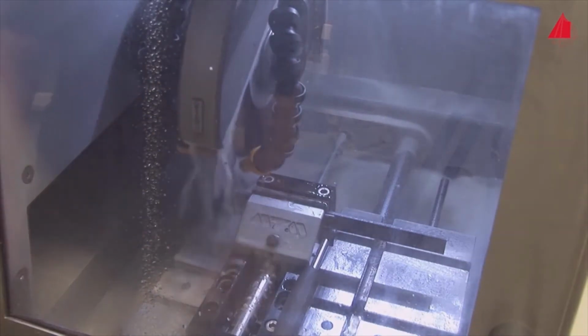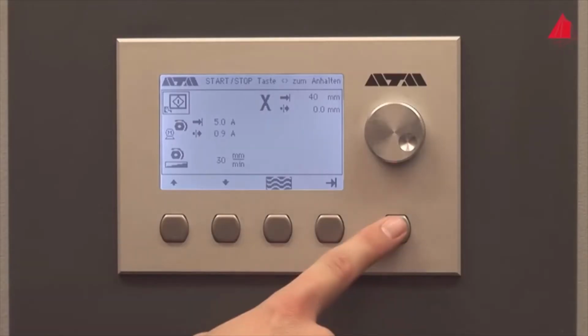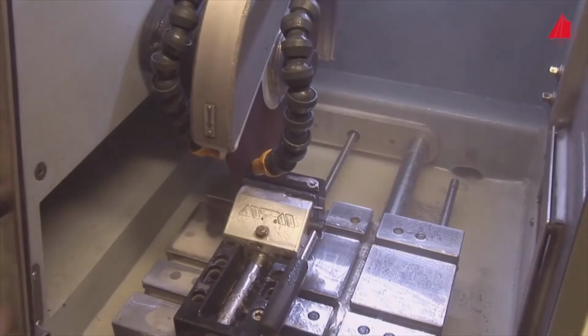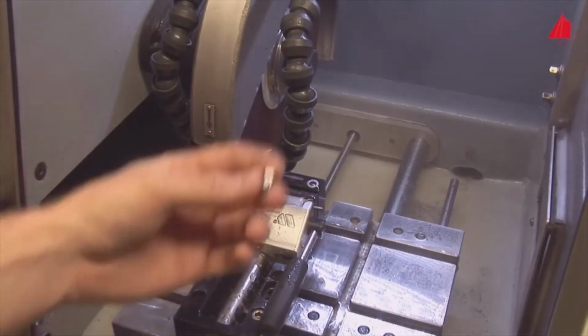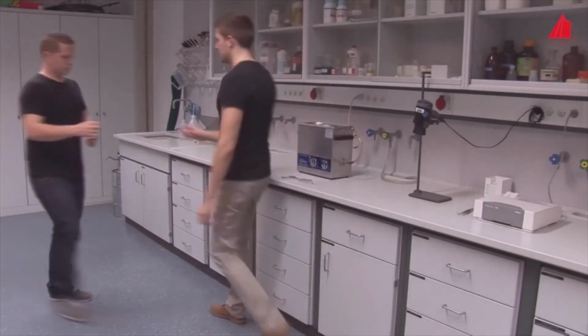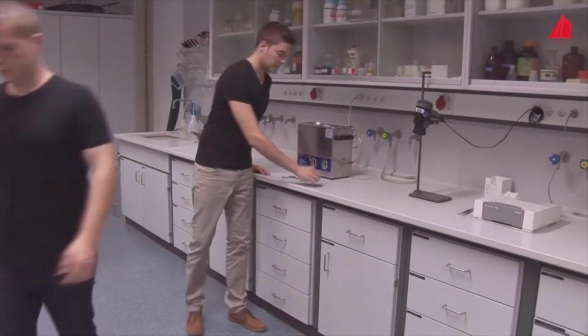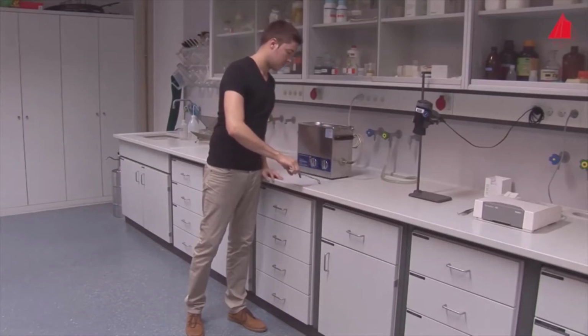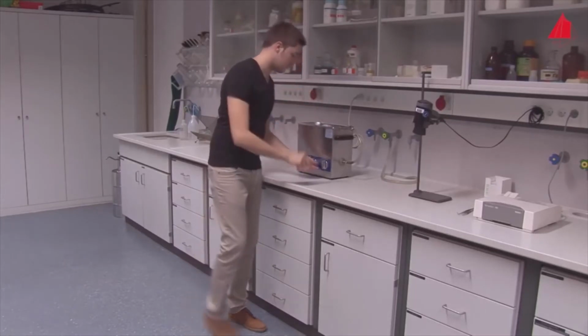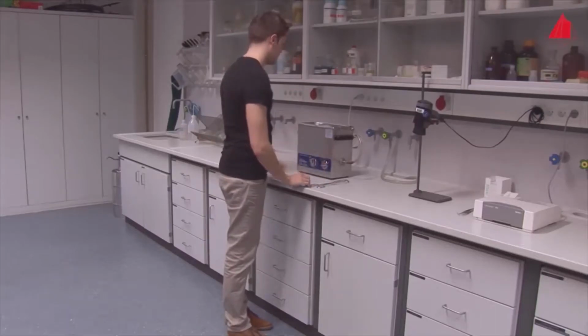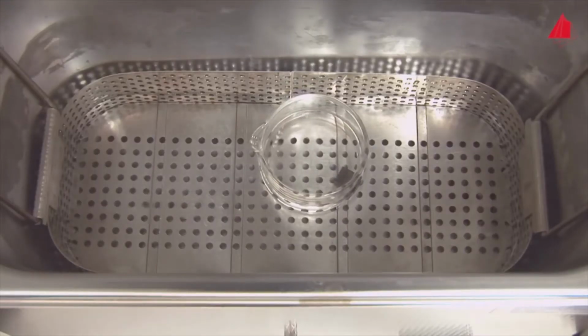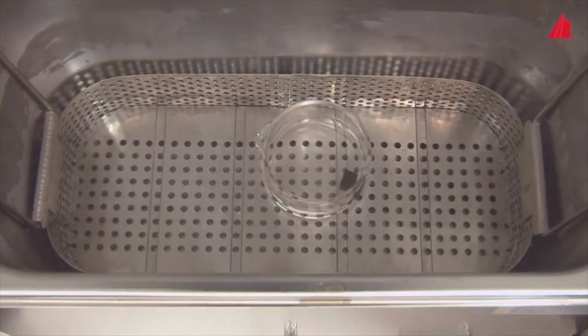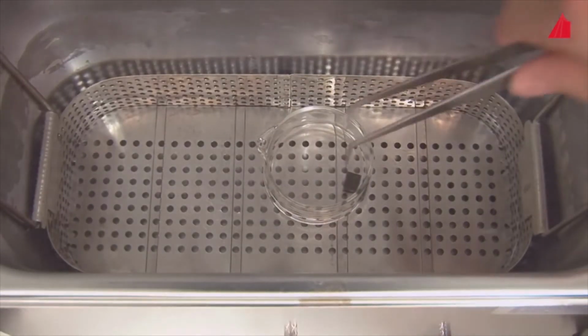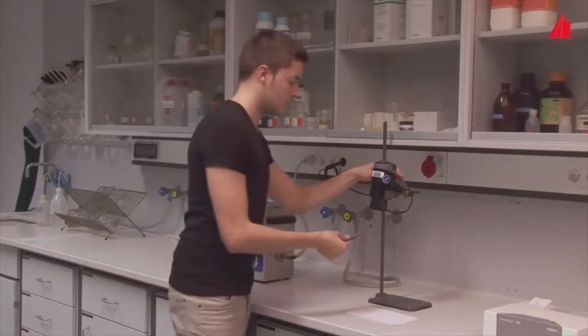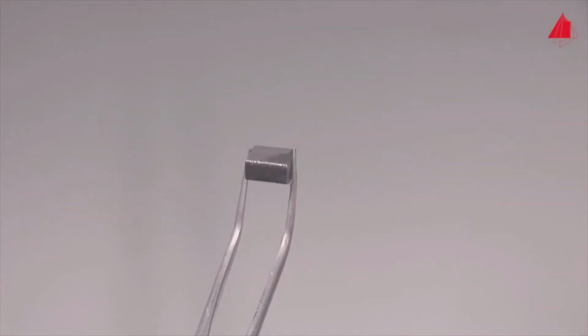Intensive water cooling and appropriate cutting parameters are important to keep the material as cool as possible. After finishing all abrasive cuts, the material tester picks up the sample and hands it over to his colleague. For further processing, the specimen has to be mounted in resin. To ensure that the resin will adhere well to the specimen surface, the specimen is placed in an ultrasonic cleaner bath for a few seconds. Alcohol and ultrasonic waves help to remove fat and loose particles from the surface. A short time under the hairdryer and the specimen is clean and dry.